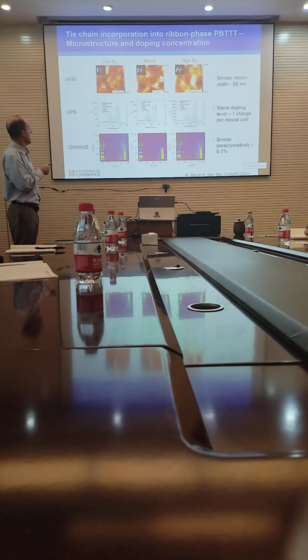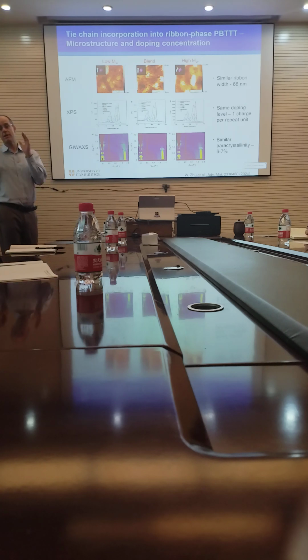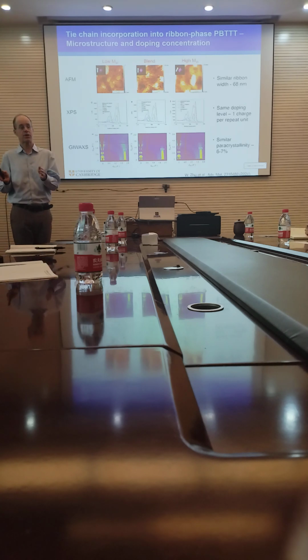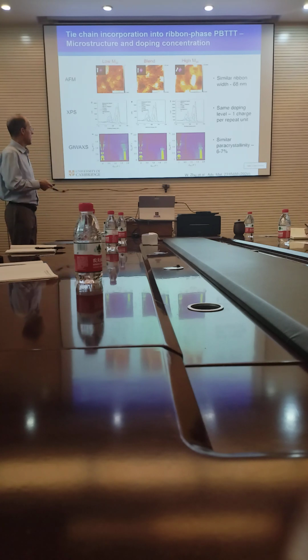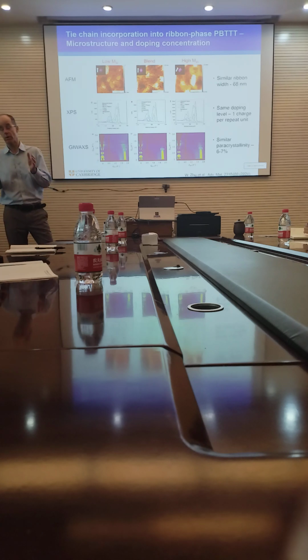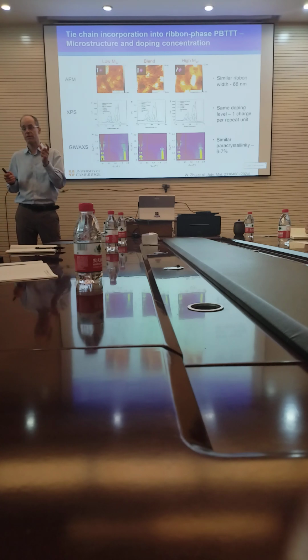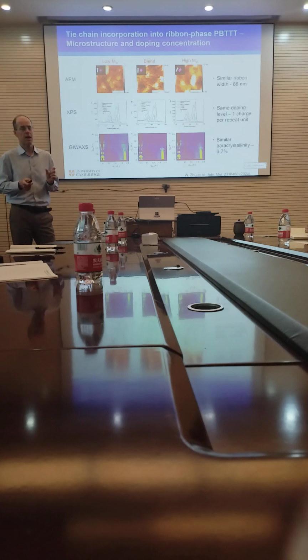In XPS, you can see that the ratio between the dopant peak and the polymer peak is about the same. So all these systems are doped to 1 charge per repeat unit, so there's no difference in the doping concentration. And if you look at the GIWAXS, you probably can't see a difference there. So the paracrystallinity in all these polymers remains low. 6-7% is a very low value. So essentially, we couldn't see a difference with all of these techniques.